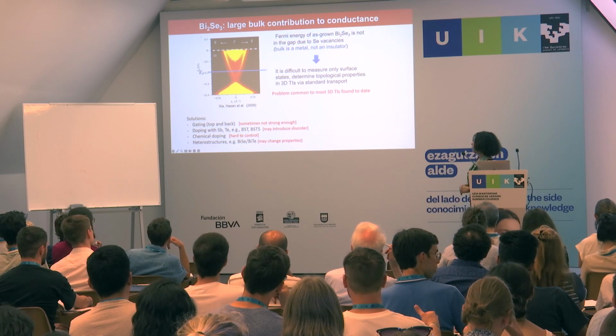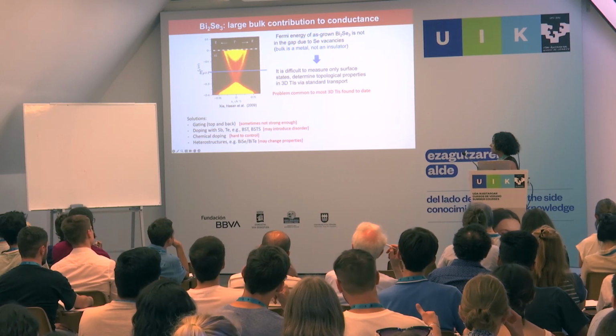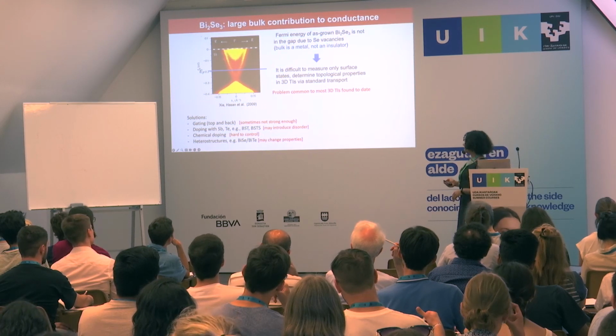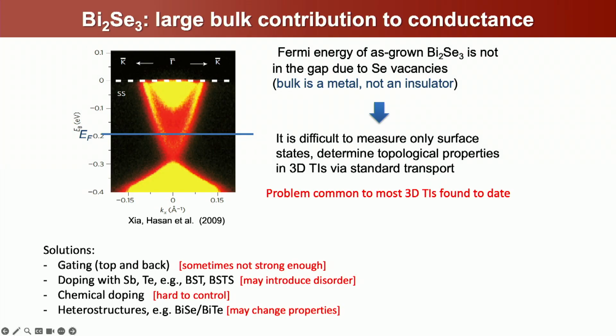Okay. Yeah, I mean, this is true for all of these systems. Once you get up into the bulk regime, it'd be like trying to measure an edge state on a metal. You see the metallic states, not the edge states, unless there are very specific properties you can find. And please do interrupt me with questions. You can also make heterostructures of these systems, like bismuth selenide on top of bismuth telluride, which is also very effective, although sometimes this does change the properties of the system as well.